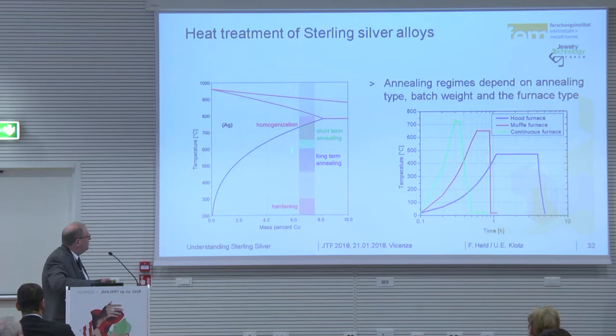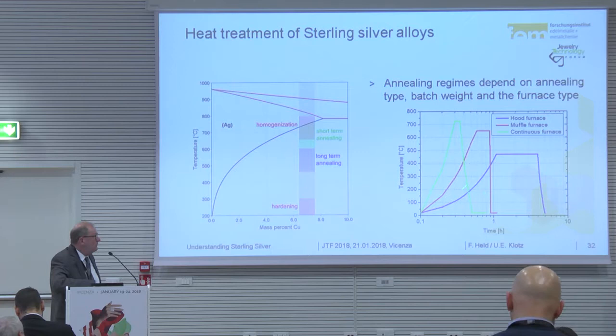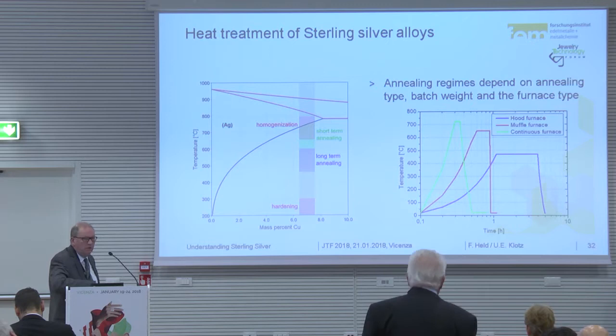Here we have again homogenization, short annealing. Here we want to show you a short heat-up. You keep it, you go down, that's the continuous furnace. Here you cannot quench so easily. Then you have the hood furnace. The muffle furnace is the second in heating up, and you keep it for a short time. Here you can quench in water so that you can later make a hardening. And you have the hood furnace, longest time to heat up, but also a long time to hold because you use a big volume of material, and then cooling down is also slow.